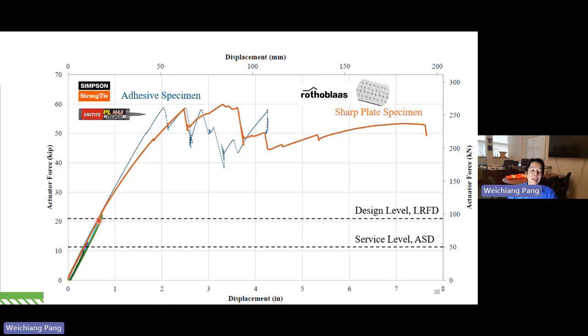What we notice here is that at the initial stiffness, they're pretty similar, right? You can't tell the difference between the two. Our loading scheme was to load the specimen to around the service load, then observe what happened. We unload it, then load it again to the so-called LRFD design level load. Then we unload it again and observe. And then at the end, we document everything and load it to destruction, all the way up. What you see like this zigzag means some of the screws start to pull out and fail, and shear cracks start to form in the glulam.